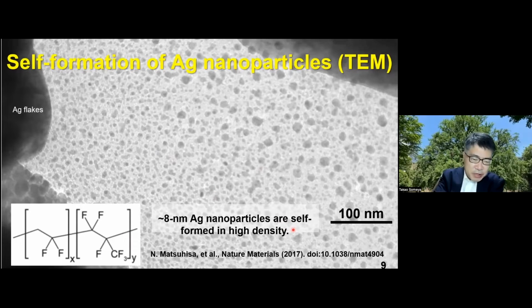Ink formulation is quite straightforward and easy. We add the silver flake to the fluorinated copolymer, with the organic solvent and surfactant, mixing everything together, and print once on the elastic substrate and anneal at 140 degrees Celsius. When we observe the cross-section of the elastic conductor, we realize the silver nanoparticles are naturally formed and densely and uniformly dispersed among the rubber matrix. This is the magic of nanotechnology. In that way, we can achieve efficient percolation conduction through silver nanoparticles that are naturally formed from a silver flake in the dimension of 2 to 3 micron.